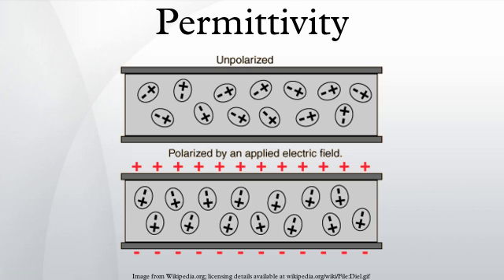Materials can be classified according to their complex-valued permittivity upon comparison of its real epsilon' and imaginary epsilon'' components. A perfect conductor has infinite conductivity, while a perfect dielectric is a material that has no conductivity at all. This latter case of real-valued permittivity is also associated with the name lossless media. Generally, when sigma/(omega epsilon') << 1 we consider the material to be a low-loss dielectric, whereas sigma/(omega epsilon') >> 1 is associated with a good conductor. Such materials with non-negligible conductivity yield a large amount of loss that inhibit the propagation of electromagnetic waves, thus are also said to be lossy media. Those materials that do not fall under either limit are considered to be general media.